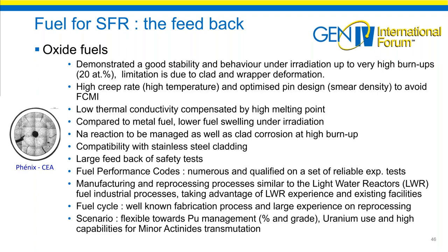So if we summarize, the oxide fuel is able to achieve high burn-up and even very high burn-up, 20 atom percent. The limit is due mainly to structural materials, namely the cladding and the hexagonal tube. A high thermal creep because of the high temperature and the optimized design lead to avoid the fuel cladding mechanical interaction. We also note a very high melting temperature, a stable and isotropic structure, and the low swelling. However, chemical interaction of the fuel with the sodium in case of clad failure has to be managed, as well as the corrosion generated on the clad at high burn-up.